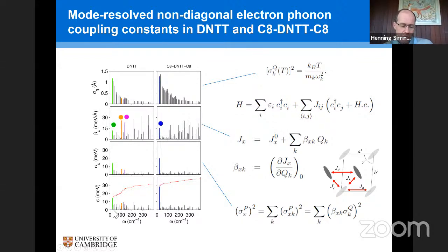And so what you can see, something that was striking that we hadn't expected, is that this histogram builds up in some cases in a rather step-like fashion. There are some modes that make a huge contribution to the thermal disorder, and there are many modes that make only very small contributions to the thermal disorder. So for example, in the C8-DNTT system that you see on the right, there is this first mode here, the softest mode, which generates almost 70% of the thermal disorder. And then all these other hundreds of modes generate only another 30%.